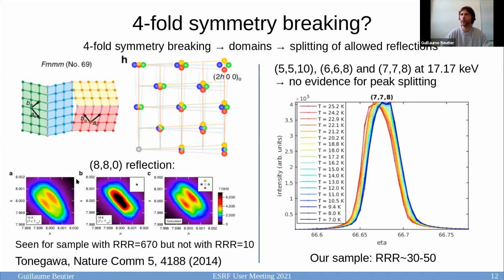So I'm just going fast through this. About the 4-fold symmetry breaking, we checked that. Tonegawa et al. observed a splitting of their 888 reflection in the hidden order phase, which they attribute to the 4-fold symmetry breaking, because if you have 4-fold symmetry breaking, you will have different domains, and they would provoke a peak splitting. But we didn't see any sign of peak splitting on the reflections we measured. One of the explanations could be that it's related to the RRR of the sample, so the quality of the sample, because in their case they looked at 2 different samples and they saw the peak splitting only in the highest quality samples. So that's not really solving the problem.